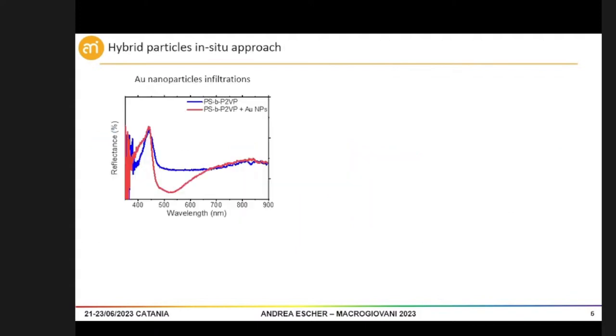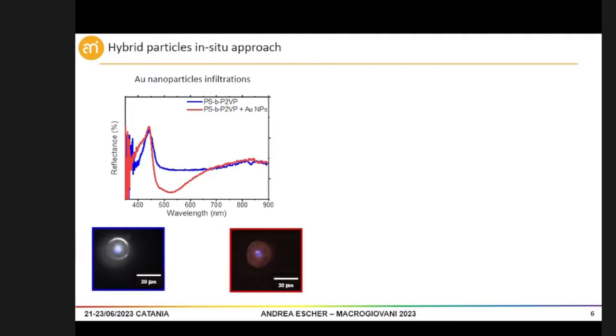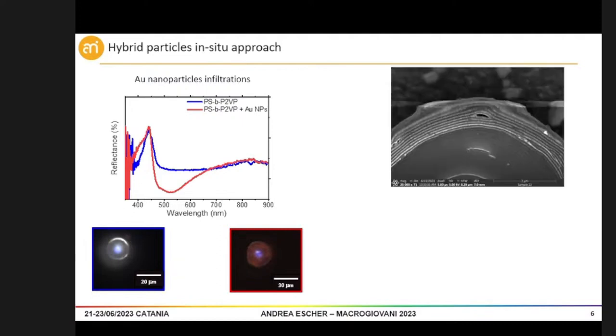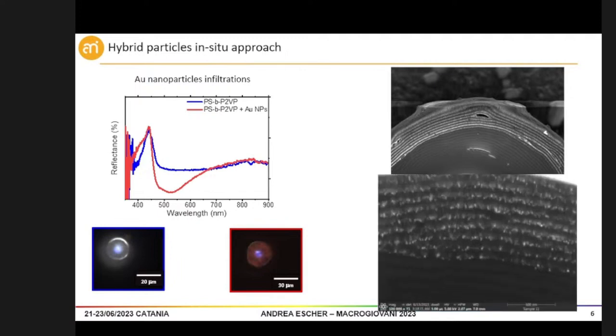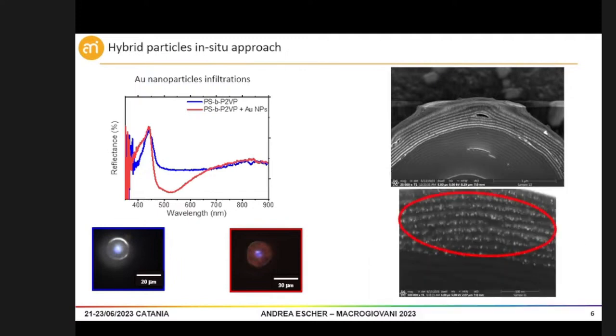Here I report the preliminary results of this research project, and I have the reflectance spectrum of these pigments. The blue spectrum is the spectrum of the sphere without the nanoparticles inside, and the second one is with the nanoparticles inside. I collect also the image of the two different pigments, and I report also the FIB image. The FIB image was taken with the FIB microscope, which is basically an SEM with a focused ion beam inside, and thanks to that we can cut this polymer sphere, and we can see inside the lamella structure. In particular, we are interested in this part, in which the white dots are the gold nanoparticles precisely located in one of the two polymer domains.